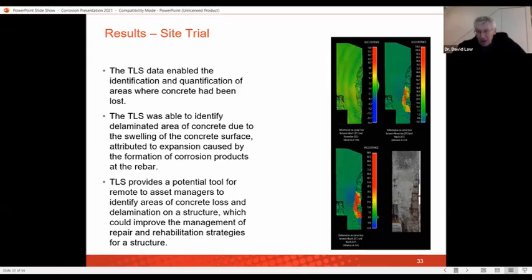And this was really good for us, in that it really showed us that with this technique, you can actually see the rust that's formed pushing off, debonding your concrete. And this is something that we're really interested in, looking at whether we can use this technique to see, not before cracks appear, but where we can see delaminated concrete. And of course, the idea is this is very useful for areas where you can't get to very easily to do visual inspections.